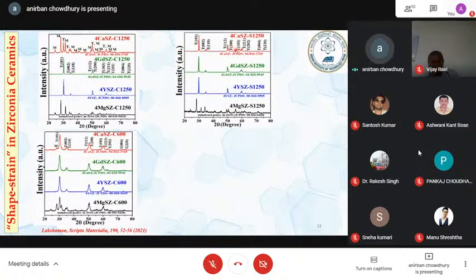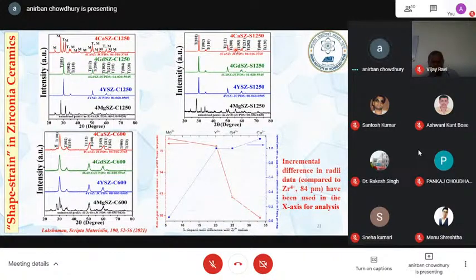So why did calcia come out as such a successful story? The reason is here. We analyzed the ratio of grain sizes from the sintered ceramic to the 600 calcined powder. And what we found was that from magnesia to calcia, this ratio is decreasing. In other words, calcia as a dopant, compared to magnesia, has the highest control in restricting the size of the sintered grains in the tablets.